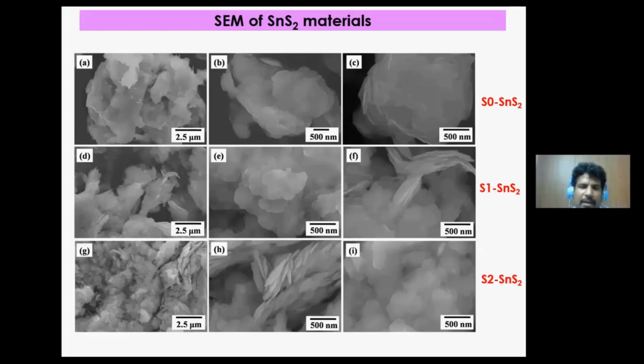Okay. So the second material, that is S1 SnS2, is synthesized using the octadecene, oleylamine, oleic acid combination. Here we can see the uneven edges of the material. The material edge is not even. And also the thickness of the material, by looking at this SEM, it looks like a disk stack. So this was confirmed with the TEM analysis, and with these pictures there are two-dimensional sheets, but there is no proper edge, the surfaces are not even. And S2 shows somewhat hexagonal shaped particles. The edges are very regular. The edges are defined. Okay, so with this, we got a little idea about our synthesized particles.